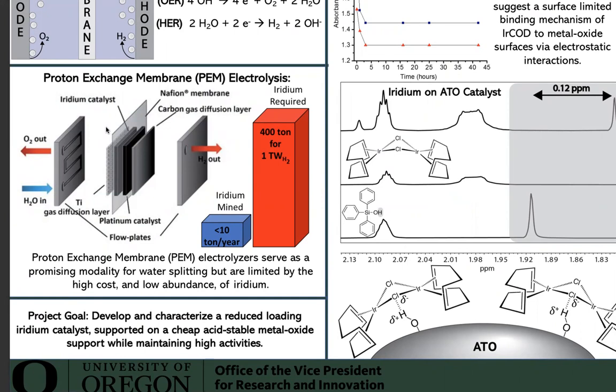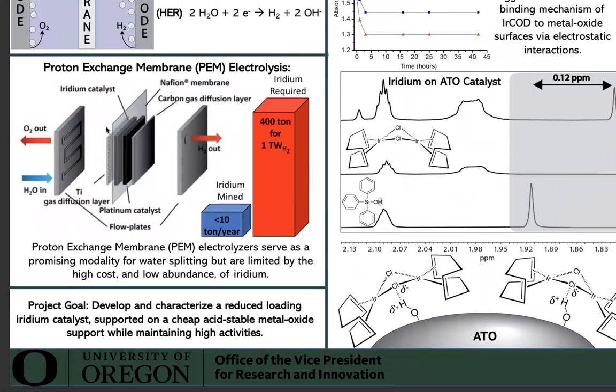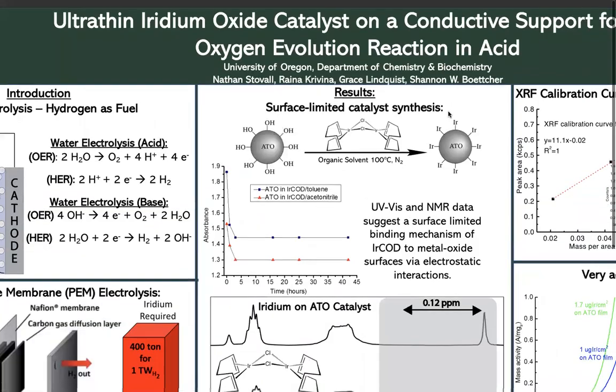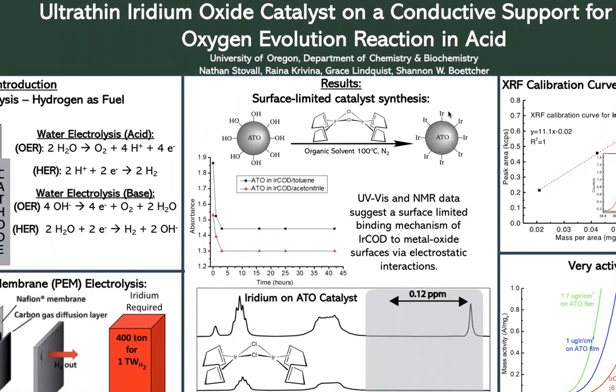To this end, we've worked to develop and characterize a low-loading iridium catalyst supported on a cheap, acid-stable metal oxide support while maintaining high activities. This led to the development of a simple synthetic method in which we soak antimony-doped tin oxide nanoparticles, or ATO, in an organic solvent with this iridium dimer we call IrCOD.